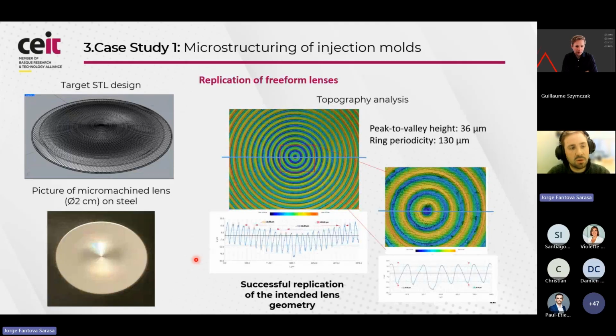So yeah, jumping straight into the details, just to show some of the results. After optimization of the laser conditions, we fabricated several lenses, in this case on a stainless steel substrate. To give you an idea, here's the target STL design of one, let's say, Fresnel-like lens. We can also see here the final lens on a macro picture, which is of a 2 centimeter diameter. And on the right here, you see the topographic images of this engraving.